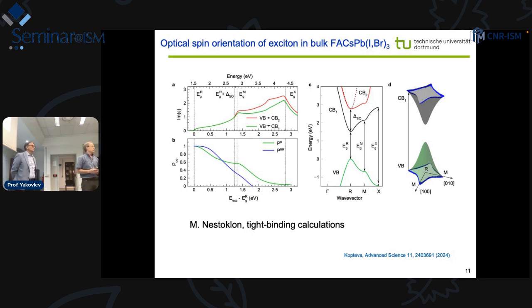That's for the bulk, okay? That's for the bulk. For small crystals? For nanocrystals. For nanocrystals, we didn't study organic and inorganic ones too much. The results shown today are for inorganic nanocrystals synthesized in glass. So they are synthesized from the glass melt, at higher temperatures. But we have some measurements of the g factors also on solution-grown cesium lead bromide nanocrystals, and the results were very similar. So at least we know that the surface doesn't play too much of a role for the g factors or for the spin dynamics.